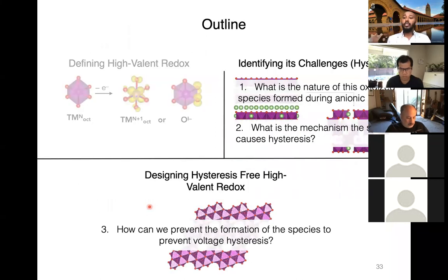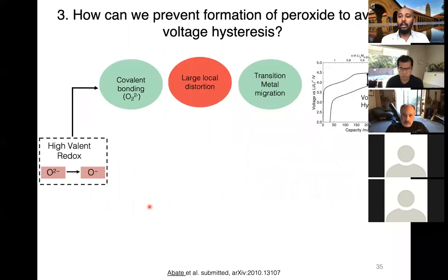So this brings me to the third question: how can we prevent the formation of peroxide in this material and the accompanying cationic disorder? Like I mentioned in the previous slides, when you charge and have anionic redox, you go from an oxide state to O-. The O- is not stable, therefore we have covalent bonding. The covalent bonding forms a very short bond length that causes local distortion that has to be limited by migration, and therefore this causes hysteresis. And this is the pathway that has been limiting us from achieving the capacity of high-valent redox.